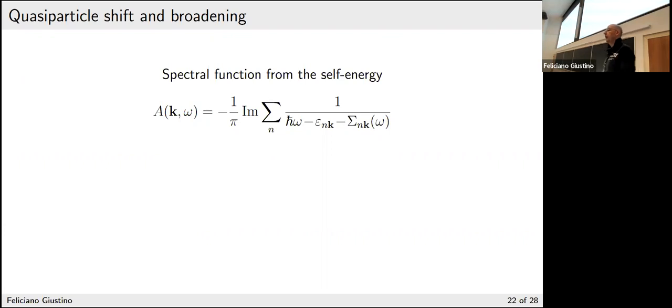So there are, I think, two aspects there. So phonons, let's say all of the things I described, I didn't mention that, to get some of the later equations, one needs the harmonic approximation where you can describe phonons as independent oscillators, okay? If you go beyond that, the equation gets much uglier, okay? There are some theory papers that explore that, but they're not being translated into computational methods because it gets really complicated. So that's basically phonon-phonon interactions.